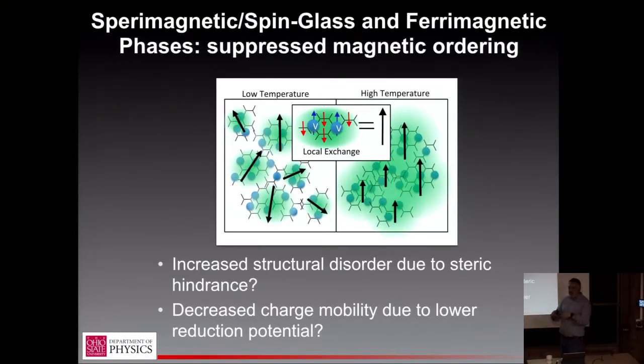We think it's very local. It's this local super exchange or double exchange mechanism, but it's only happening within one or two lattice sites. And maybe one way to think of this is, and again, there's a lot of unknowns here, so I could be totally wrong, but this is the way that we think about it. You know, if you imagine each of these locally ordered clusters as a hopping site, and hopping between these turns on as you go to high temperature.